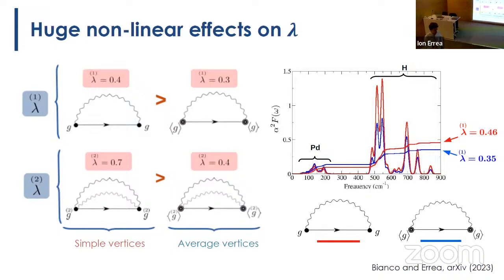Okay, so basically we treat the electrons at the level at which we treat the Born-Oppenheimer energy surface. If this Born-Oppenheimer energy surface is treated at the quantum Monte Carlo level, we would have all correlations included. If we have it at the LDA level in DFT, the correlations of the electrons would be treated at that level. So in that sense, the machinery is independent of what happens to the electrons. It is true that in most of these cases we were working with DFT at the PBE or standard DFT level. But I think the problem is there, not in this machinery itself. It's in how you are including the Born-Oppenheimer energy surface. So you will need to go to higher orders.